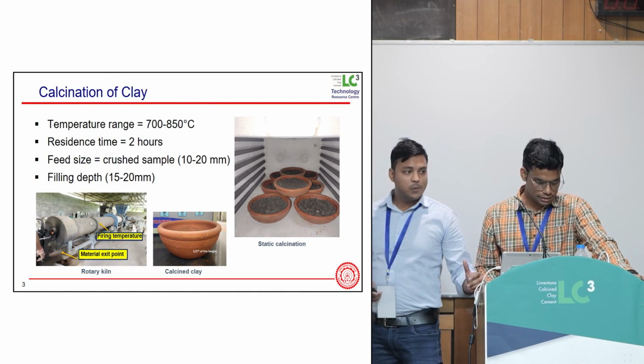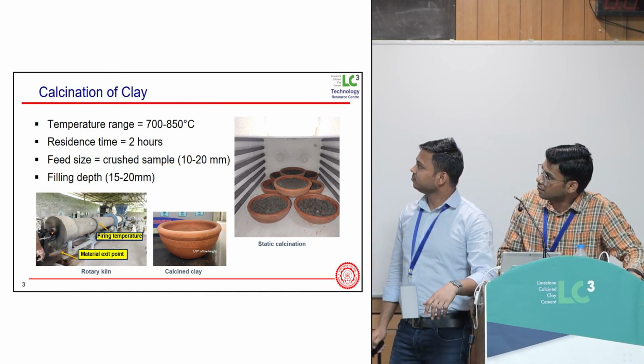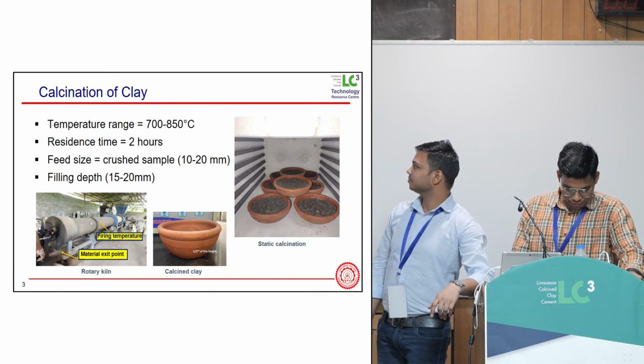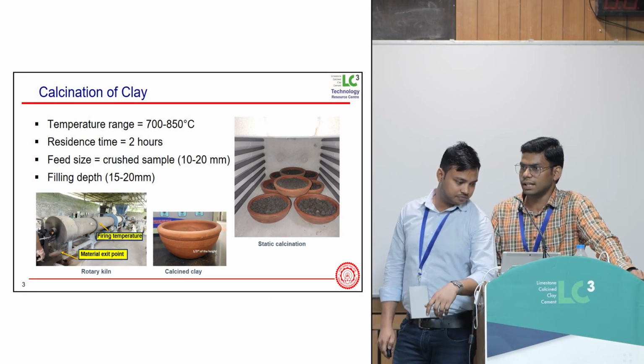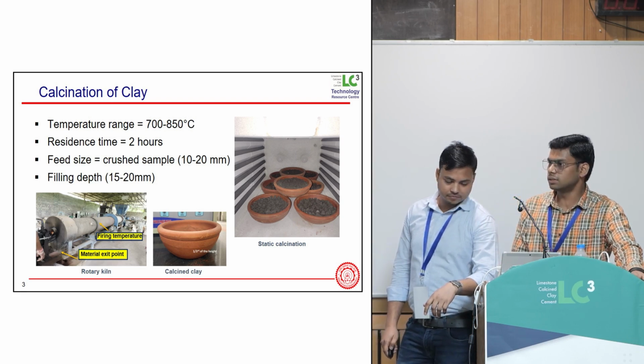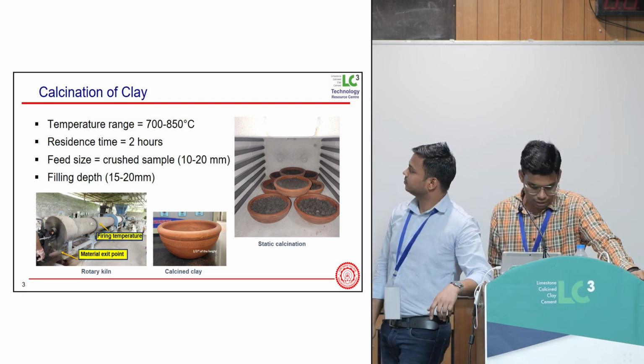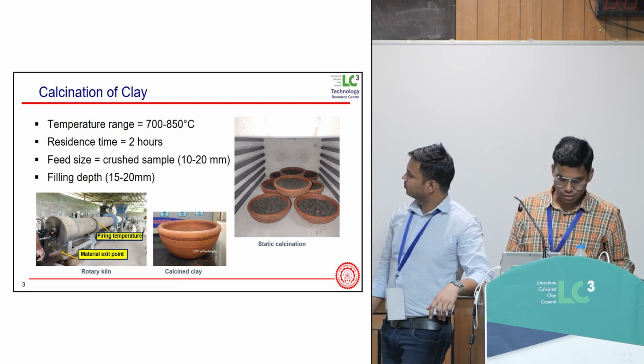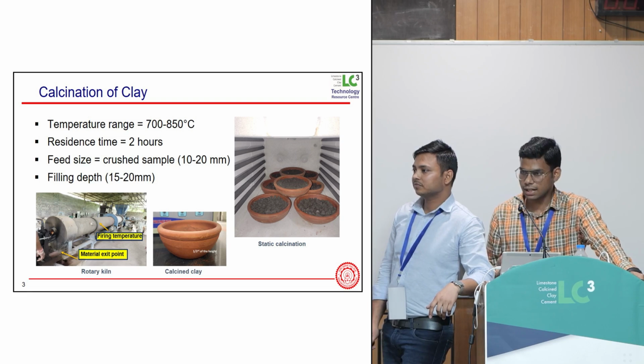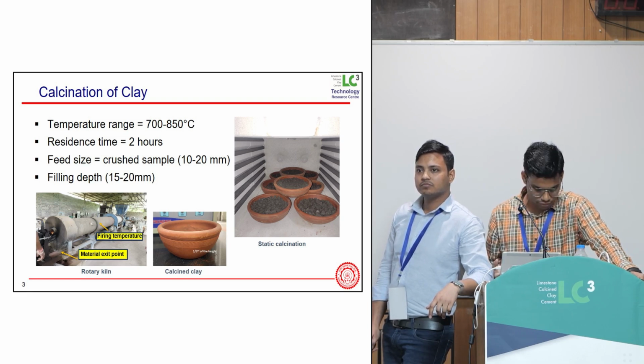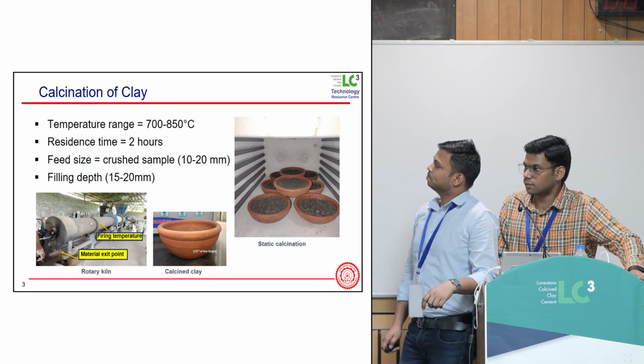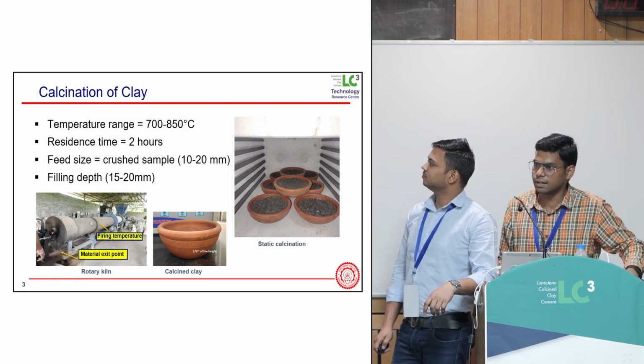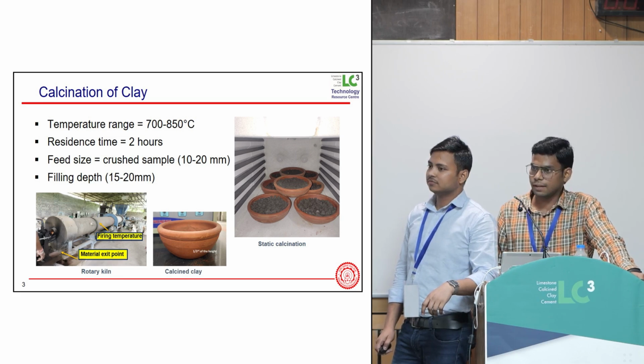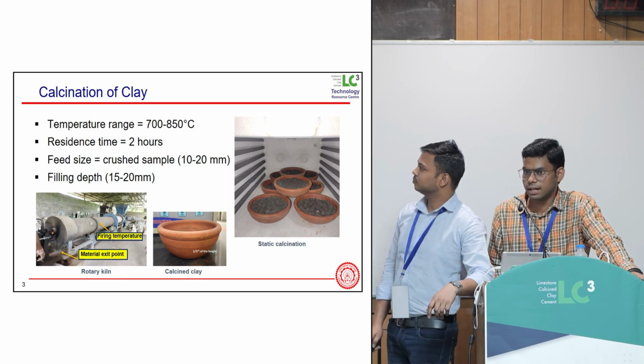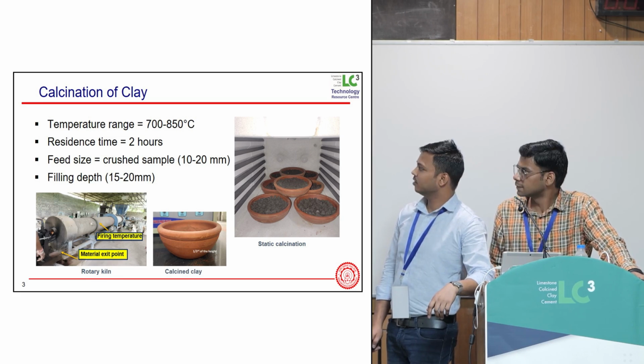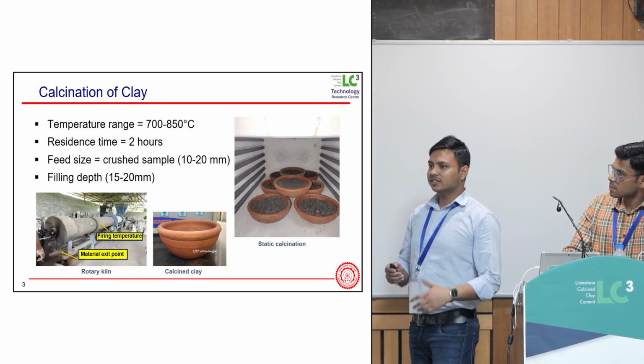The calcination of clay is generally done in the temperature range of 700 to 850 degrees Celsius. But in our lab, we generally calcine the clay at 800 degrees Celsius, and we get good results in terms of lime reactivity and compressive strength of LC3. But for some clays calcined at 800 degrees Celsius, we didn't get good results. So we checked the quality of calcination, and we found that our clay was under calcined. So we increased the temperature up to 900 and calcined again, and we found good results. So the temperature does not remain the same always.